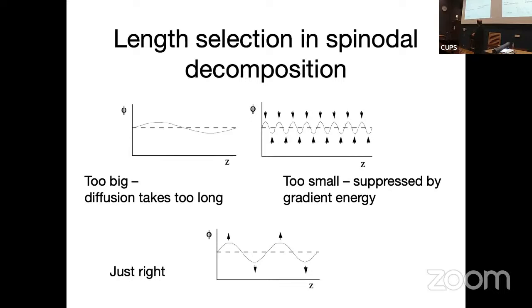If the fluctuations have a very small wavelength, then that will lead to lots of interface. That's got a high energy, so those ones are suppressed. If it's a very long wavelength fluctuation, it just takes a long time for the molecules to go from the bottom to the top, as it were. So there's always a just right. There's a length scale selection mechanism that gives you a characteristic length scale.